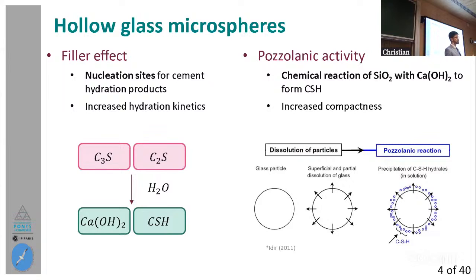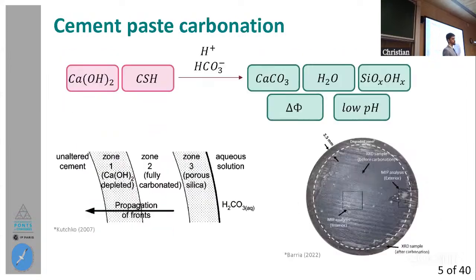But the cement will not only be subjected to these conditions of being partially replaced with the spheres, but also to the conditions existing in a CO2 injection or legacy well. In this regard, we have to take into account cement paste carbonation, which is basically the idea presented here, in which calcium hydroxide and CSH will react with carbonic acid to form calcium carbonate, water and leached silica. This will also result in a change in porosity and a decrease in the pH due to the consumption of calcium hydroxide. This will be important later on, that's why I'm focusing there.